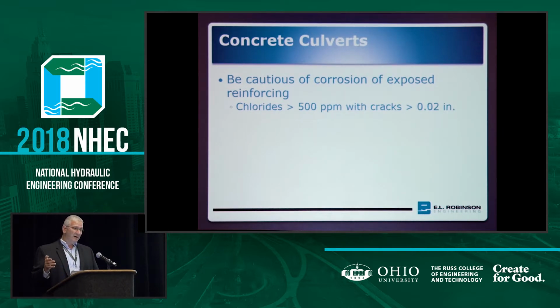As an example, most states in the country who have done durability studies, resistivity was a significant factor. In the Ohio study, the first one was done in 1972, the last one was just completed about 2 years ago, and resistivity was found not to be a factor. So that type of variability exists. It's natural variability, and it's different environmental conditions that you run across in different states. Okay. So anyways, chlorides greater than about 500 parts per million, and cracks greater than about 0.02 inches, so greater than about 2/100 of an inch. With chlorides greater than 500, you can get a situation where you're actually starting to break down the reinforcing steel inside of the concrete pipe. Okay.